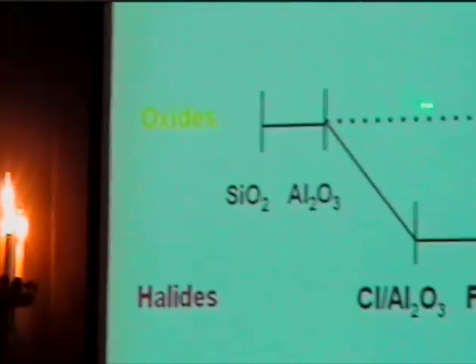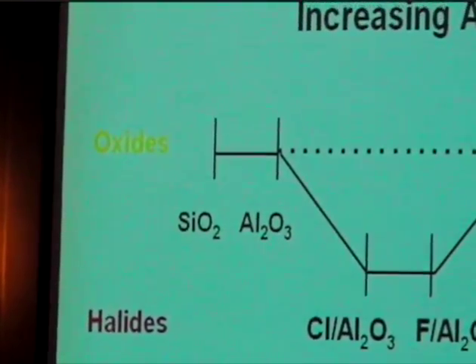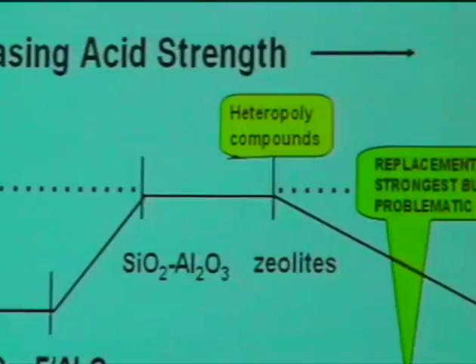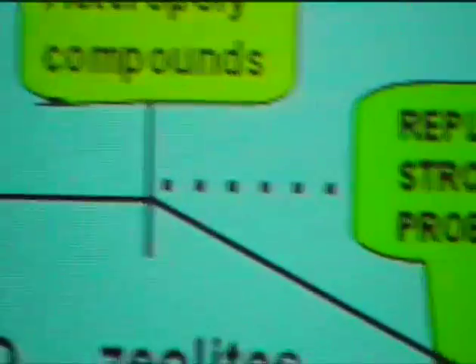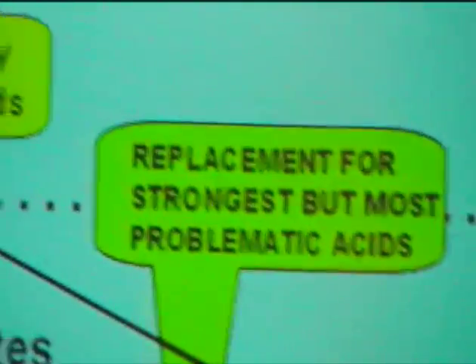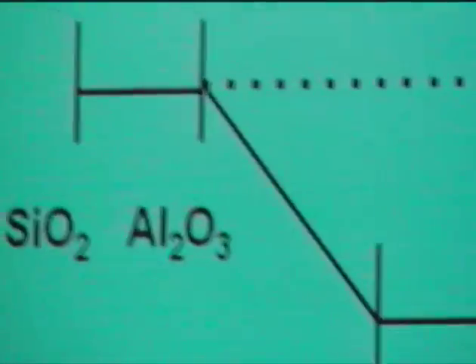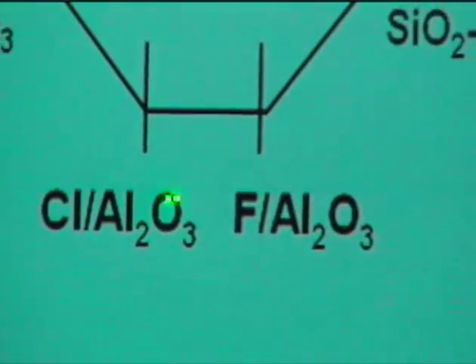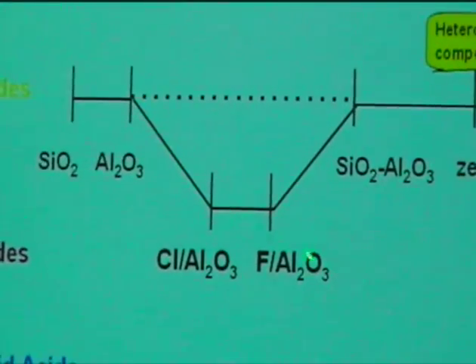Okay, if you go along the top axis here, I like to look at that as basically just where the oxides are and what we have available. So we start out with silica, non-acidic, alumina, a little bit of acidity. People then try to get to a little bit increased acidity from that by adding halides. So I'm actually using that for this halide axis here. And you have chloride and fluoride alumina.